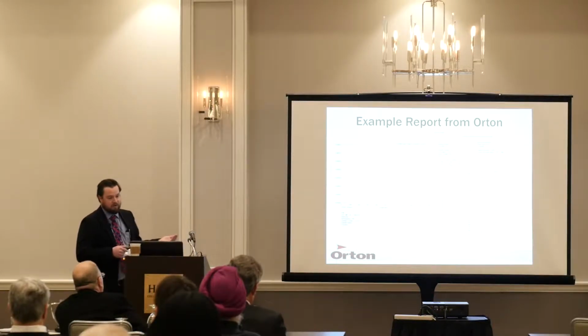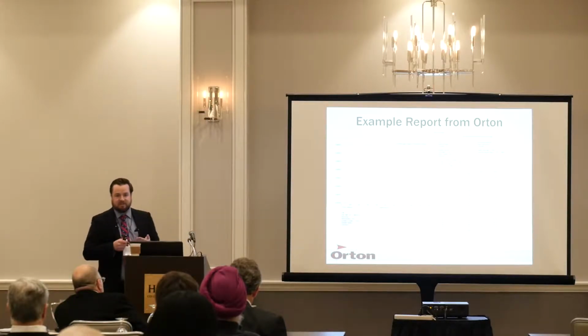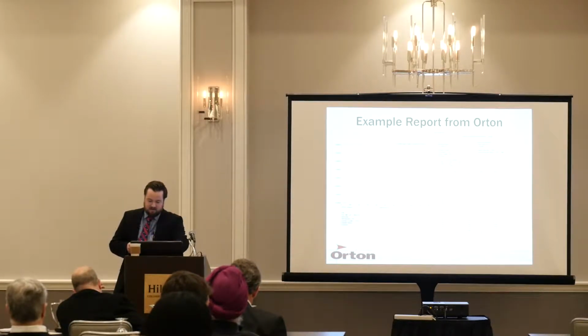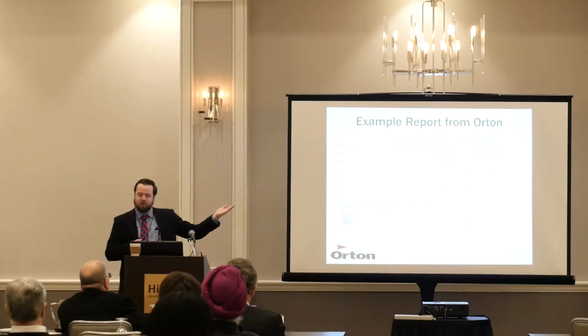This is where you start to qualify different materials for different CTE values. So as I was showing you earlier, platinum has a plus or minus range of 8 parts per million per degree C. I think actually it's 10, but it's plus or minus 2. So you start to see an actual very definitive number to say what a material CTE is. We'll see in a second the calculation that goes into it, and it's not as straightforward if you have a material that's not performing quite like this. You can see here, your CTE starts off at a slightly different range, but it levels out right around 17, 18 parts per million per C. So you can see a linear performing material, but they start to slope or curve, and so you have to understand what range you're looking at.